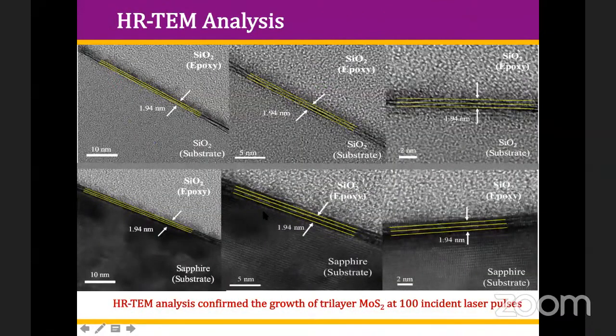Again, we use a high resolution transmission electron microscope just to see the thickness of our grown film, because we had checked with the AFM. Now we tried with the HRTEM, which is a more precise technique to identify the thickness of the layer. In this case, the substrate was silicon dioxide, and on the bottom side, the substrate was sapphire. In both cases, we got a thickness of around 1.94 nanometer, which corresponds to trilayer. So these are the HRTEM images for 100 shots of the laser pulses, which lead to the trilayer deposition of MoS2.